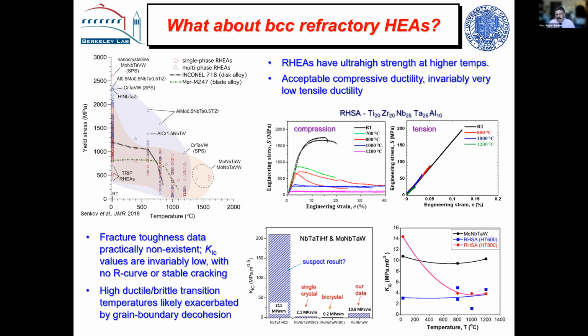ductile-brittle transition temperature. There are only 3 toughness results in the literature, by the way. One is on a bicrystal and a single crystal. One is on a material which is this niobium, titanium, tantalum, hafnium, and they claim the toughness was 211 megapascal root meters. If that's right, then that's worthy of a Nobel Prize almost, but I don't think it's right. But there is a big problem here with being able to measure these; they're very, very low. This is a bunch of ones we've looked at, and they hover around 2 to 4. Sometimes they get to 10 to 15.